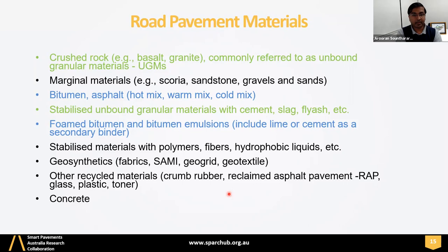UGMs can be stabilized with various binders, right? Which include cement, slag, and fly ash. And Australia is at the forefront in using cement stabilized UGMs, because their pavements have already reached their design life, and they are using in-situ stabilization of the existing degraded unbound pavements to strengthen the pavements for the forecasted traffic. Commonly, GP cement is used, and GB is also used depending on the urgency of the traffic opening.